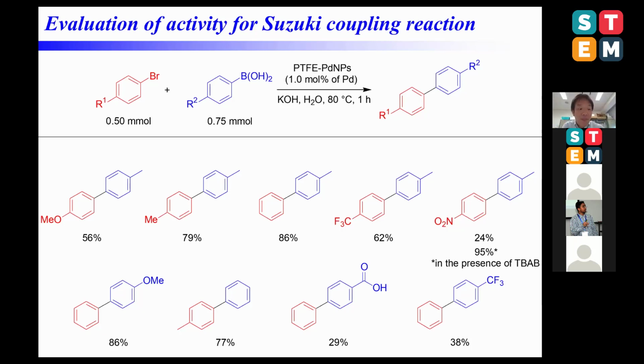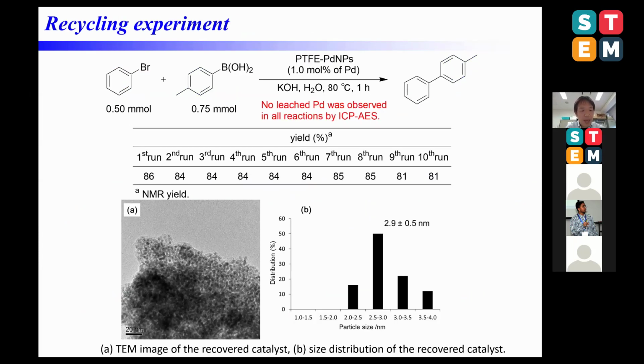So first, we evaluated the catalytic activity of PTFE-supported palladium nanoparticles using the Suzuki coupling reaction as a model reaction. When the reaction was performed using several bromides with various substituents, both the electron-rich and electron-deficient bromides were reactive, affording the desired coupling products in high to moderate yield.